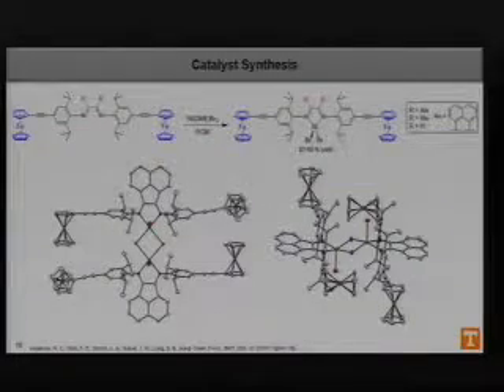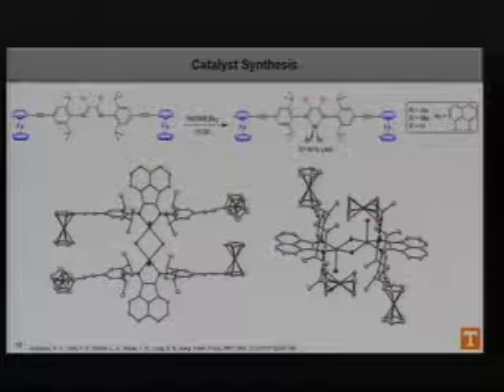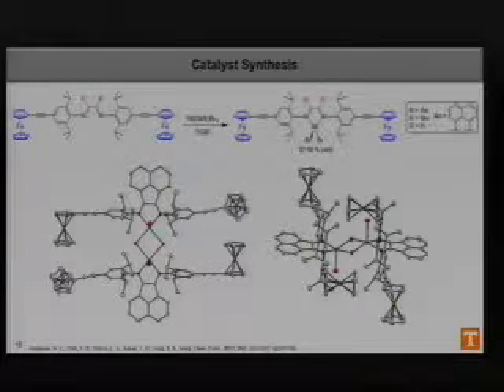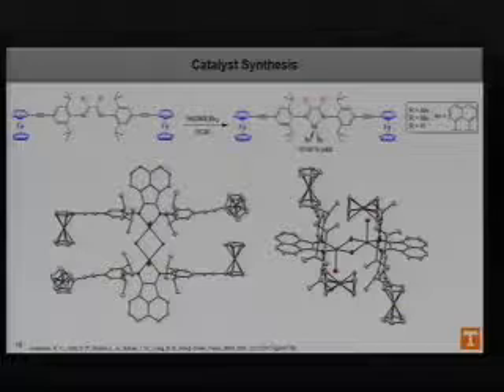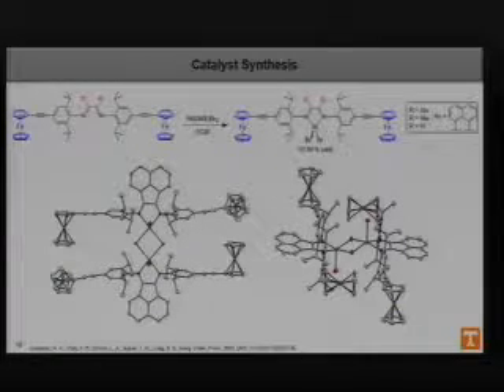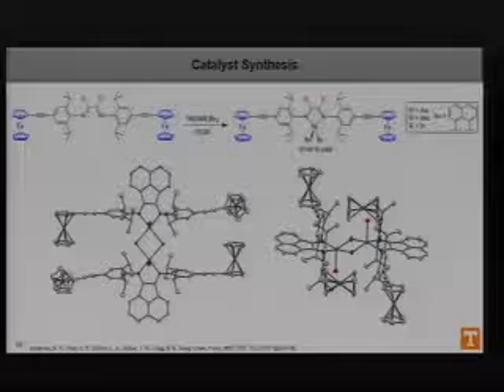So once we got this ligand, we then metallated with nickel dibromide, and we were able to get this crystal structure thanks to some help from Gaia and Dr. Jenkins' group. And it dimerizes in its crystal state. As you can see, here's one nickel center and here's the other. And this is actually the same crystal structure as Brookhart's original catalyst that was released too. It does the same dimerization when it's in its crystal state.